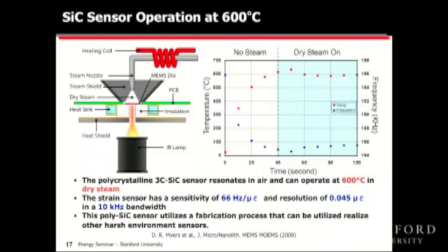Once it hits 600 degrees C, we turn on the dry steam, and it continues to resonate with no significant changes in the resonant frequency. So this is telling us that we can actually make functioning electronics at 600 degrees C in hot oxidizing environments, similar to what you would find in combustion environments, for example.